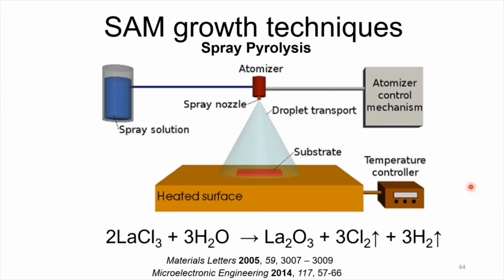The last one we actually tried, and looked very promising too at some point, was spray pyrolysis. So spray pyrolysis, what you do is you have very small droplets through an atomizer, and these droplets get in contact with high temperature surfaces. This allows for rapid evaporation of your solution, like water or your solvent, leaving behind just a thin film of whatever material you want. In particular, we were looking at lanthanum chloride water solution, and the moment it hits this high heat surface, I'm talking about 400 degrees, 500 degrees Celsius. So really high temperature surfaces.